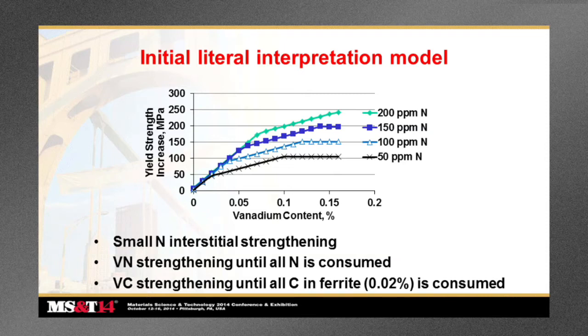After you run out of nitrogen, then you get vanadium carbide precipitation strengthening, not so much because the precipitate itself is any different, but the formation of the precipitate is much slower and tends to be coarser and less effective in strengthening than the vanadium nitride. So it continues to strengthen, but at a somewhat reduced slope. So once you essentially have exhausted the available nitrogen, now you're strengthening with vanadium carbide precipitation.